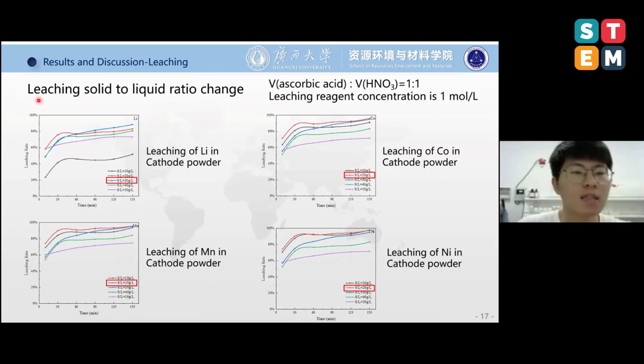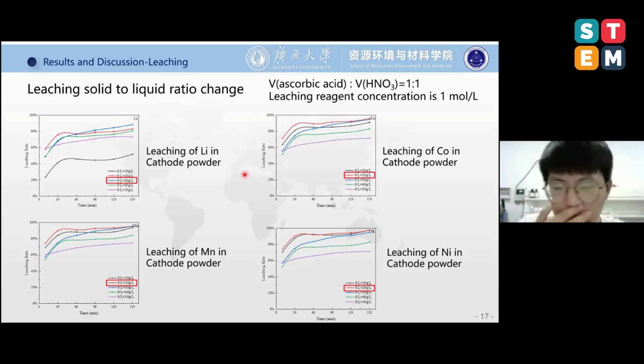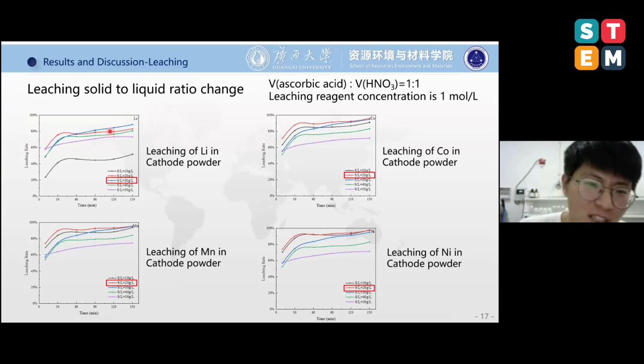And then we study the solid to liquid ratio. The volume ratio is 1:1. The reagent concentration is 1 mole per liter. For lithium, when the solid to liquid equals 30 grams per liter, the leaching rate is the highest. But for cobalt, manganese, and nickel, the solid to liquid ratio equals 20 grams per liter to get the highest leaching rate. So we choose the 20 grams per liter as the solid to liquid ratio.